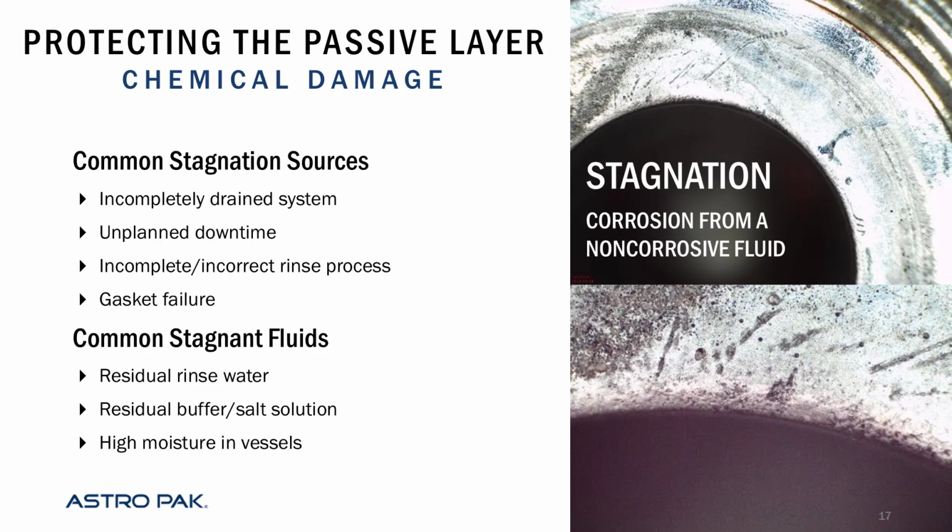The most common one though, and shown in these photos of a diaphragm valve that failed, is a gasket failure. So you may have a pretty non-corrosive process fluid so long as you're CIPing pretty often. But if you leak through a gasket in a perfect crevice site, that sealing face can be eaten apart over the course of a weekend, I think is actually what I got these 2 photos from.